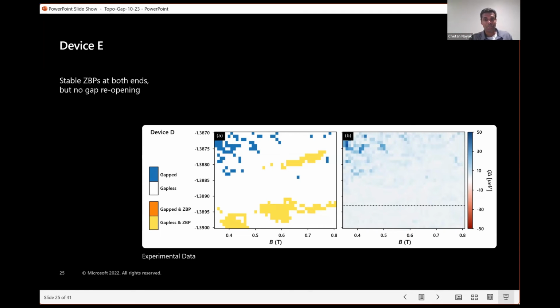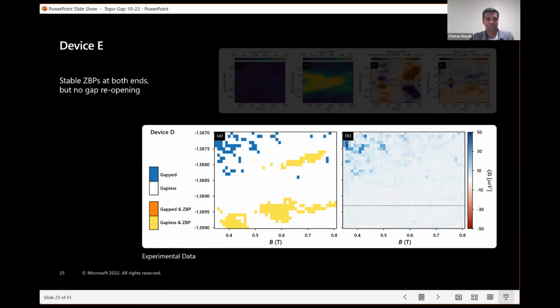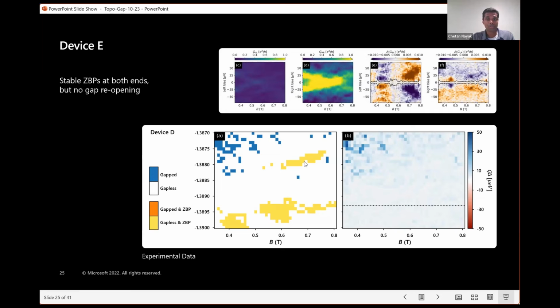In this particular device, there's some natural variation in what the density of charge defects is in our devices. This one happened to have a little bit higher defect density, but even the ones with lower density, the yield isn't perfect. It's a mesoscopic system, it's a finite size device, and the disorder levels are small, but not extremely small. Okay, here's what the transport data looks like, cut through here. You can see there are stable zero bias peaks on both sides, but the gap really never reopens. It gets small and then kind of stays small.